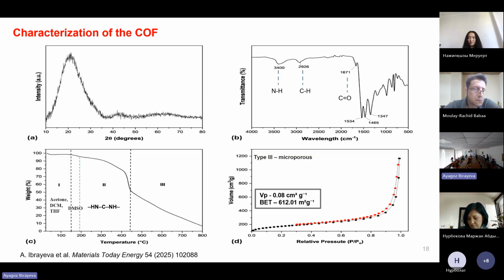It can be a fingerprint from the terephthalate, because in that structure it has a C=O bond. So some initial product can stay in there. Yeah, because here we can see the triazine ring's successful formation, and this small peak can be the presence of the terephthalate, because we can see in the structure it has rings.